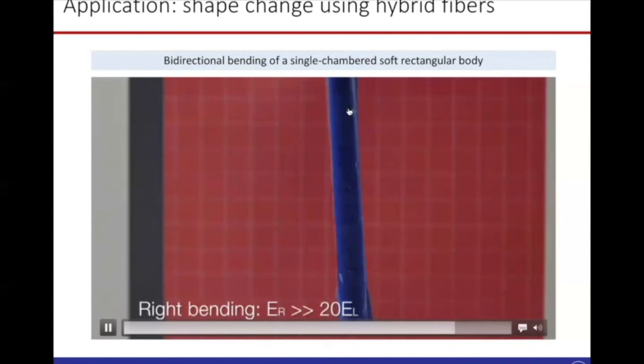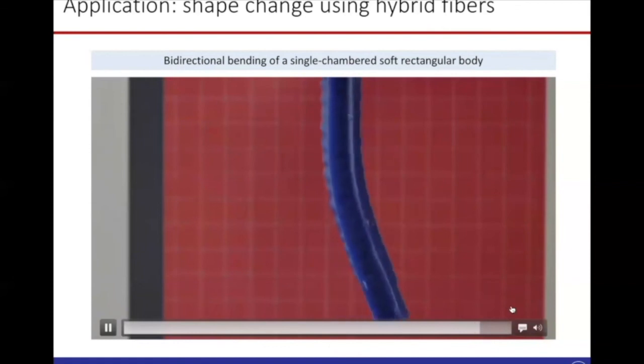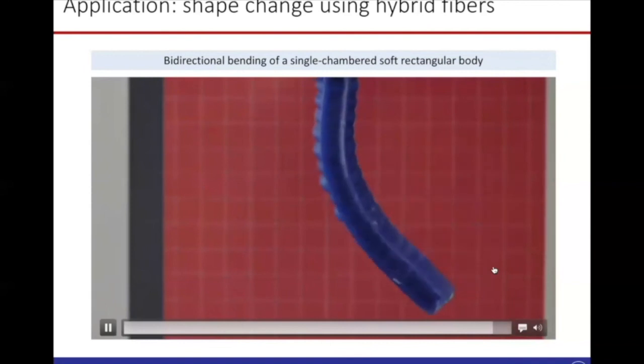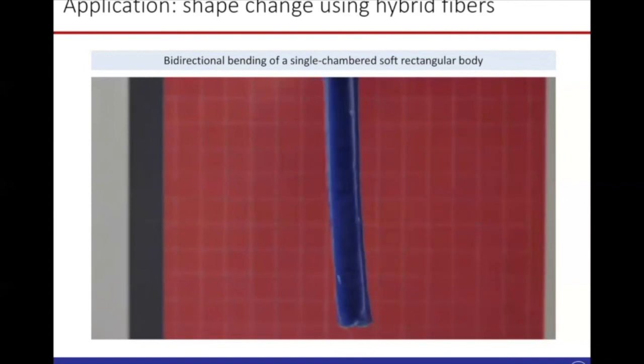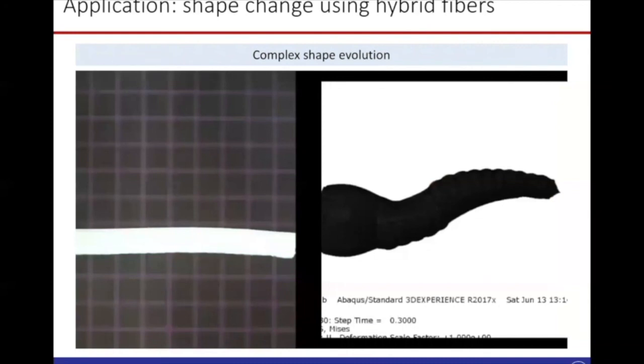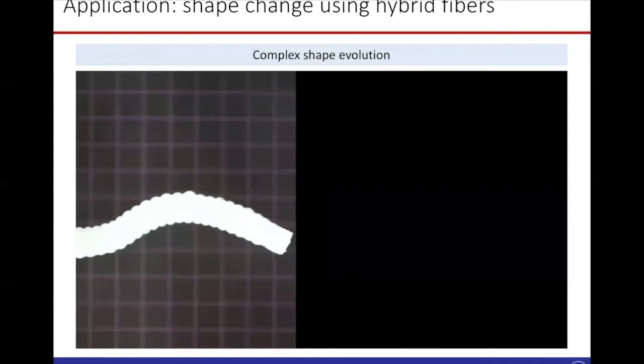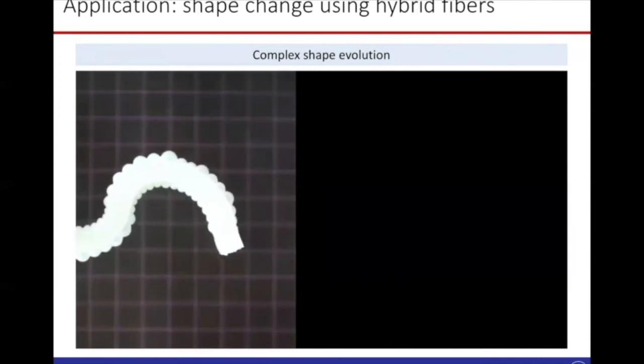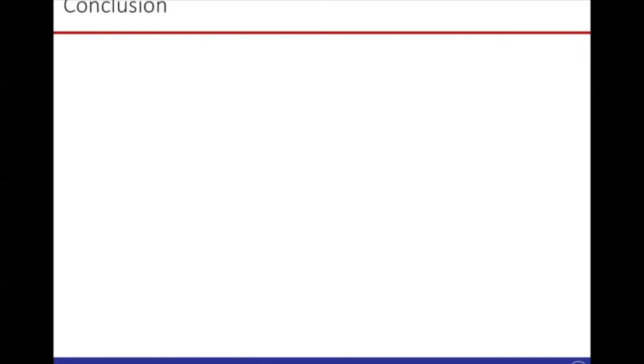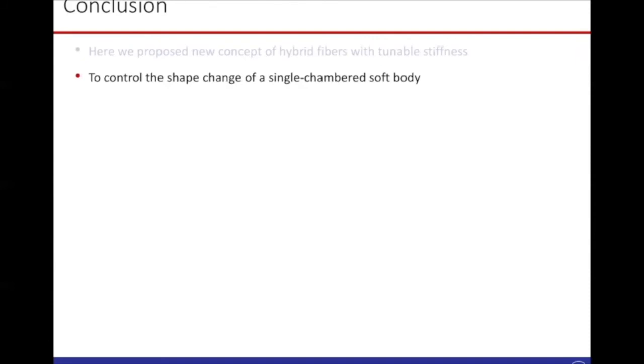So now it's completely cooled and stiffness is recovered. Then you unlock the fiber here, and then it can bend towards the right side. So in that way, you can control the movement direction by controlling the membrane stress. Now, this is a complex shape evolution. Here, they have multiple fibers inside, and you can produce a complex shape change in the soft body. Now, as a conclusion, here we proposed a new concept of hybrid fiber with tunable stiffness to control the shape change of a single chamber soft body. So just through stiffness change, you can replace this multi-chamber system with a single chamber system.